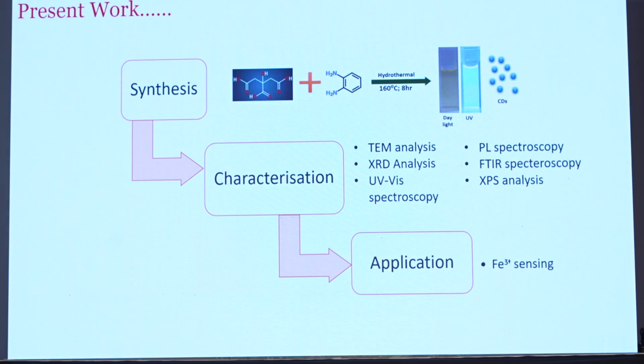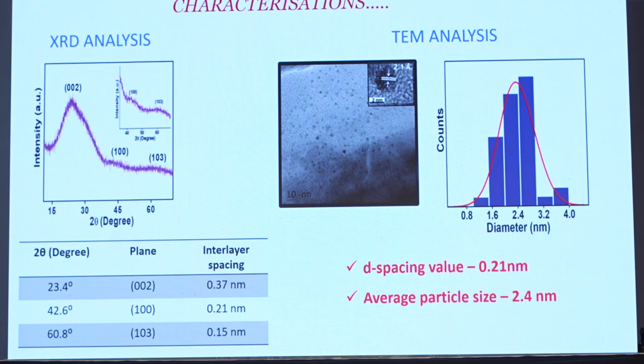It is well characterized using TEM, XRD, XPS, FTIR, and UV spectroscopy, and the synthesized carbon dot is used for ferric ion sensing. Moving on to the characterization. XRD analysis shows that it contains 3 peaks at 23.4 degree, 42.6 and 60.8. The peak at 23.4 corresponds to the 002 plane with interlayer spacing 0.37 nanometer, which is similar to the interlayer